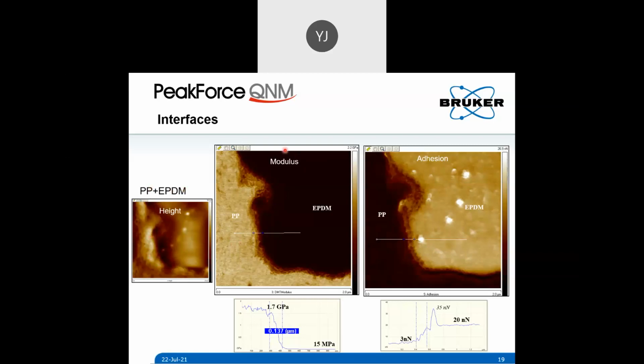Then once you look in the modulus, it's very clear, right? This is the very hard material, and this is much softer, and you can even quantify them. So it's 1.7 gigapascals, this 15 megapascals. It's a huge dynamic change there. And you can also look at the adhesion channel, and here the contrast is inverse, whereas the EPDM, which is a softer material, has a much stronger adhesion to your cantilever than the PP, right?